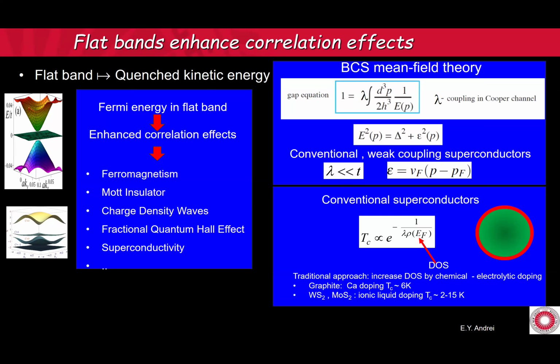You can do chemical doping, you can do intercalation, and for example, graphite calcium doping gives you a TC of about 6 Kelvin, and with electrolytic doping, you can dope TMDs using ionic liquid, and you can get up to maybe 10 or 12 degrees.